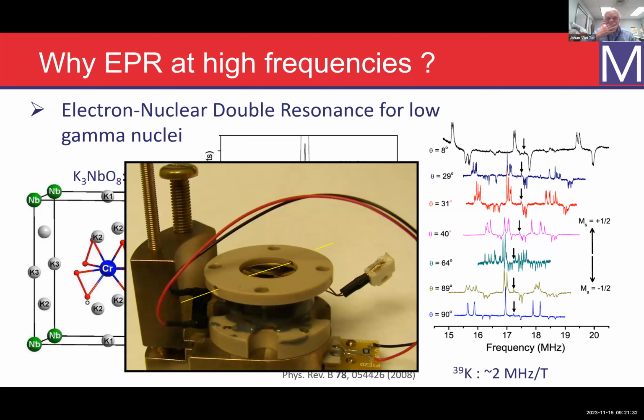And this is just to show how this was measured experimentally. We have, in this case, a Fabry-Perot type resonator, which is mounted below our corrugated waveguide. You can kind of see the mirror below there. The ENDOR coil was actually a wire going through a quartz capillary that went through one of the nodes within the resonator. And the sample was glued to the outside of this quartz capillary. So it was not really an ENDOR coil in a sense, but because the sample is so close to the RF wire, it works actually pretty well, as you see.